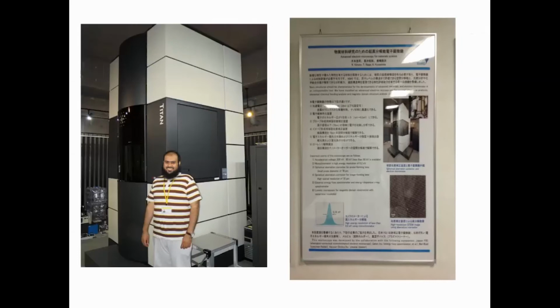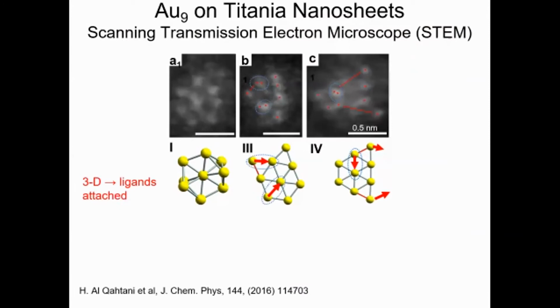We use the scanning transmission electron microscope, which is aberration corrected, so we can reach atomic resolution. This atomic resolution depends on the electron beam diameter, which is around 0.1 nanometer, applicable to imaging the atoms themselves. This was at NIMS in Japan. And we can show our gold nanoclusters deposited on the titania nanosheet.